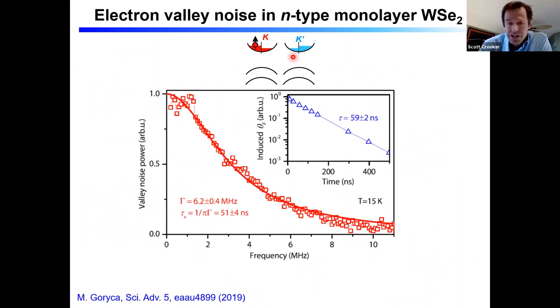We can now populate this with electrons and do the same sort of measurement. You see data that looks the same until you notice the x-axis is an order of magnitude broader. So it's a much broader noise signal for electrons, telling us that the characteristic correlation time is much shorter, only about 50 nanoseconds or so.